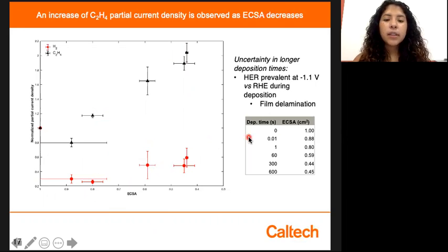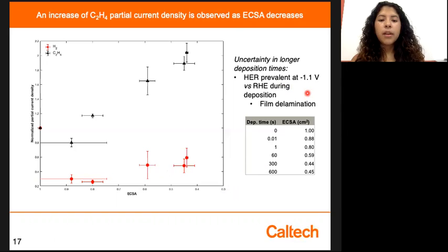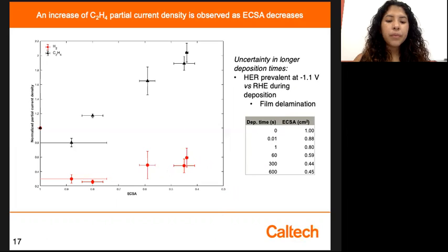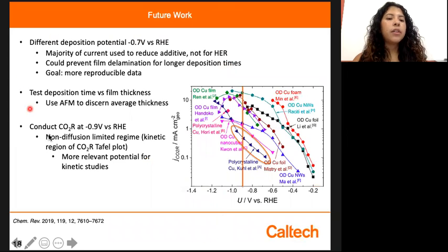A challenge that we face when running longer deposition times is that there's more HER happening on the copper surface, and when HER is happening, there's bubbling, which could lead to film delamination. So a way we could modify this project to further look at the intrinsic activities is to deposit the film at negative 0.7 volts versus RHE, so most of the current will be used to reduce the additive, hopefully preventing HER. Then we would possibly get more reproducible data for longer deposition times.